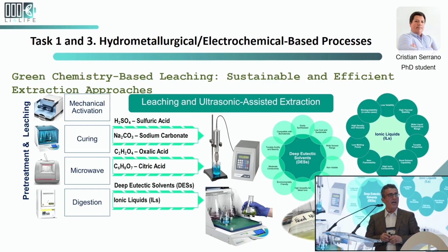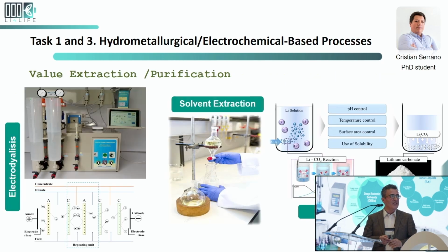These are our hydrometallurgical electrochemical processes. We are currently working on that and using different reagents: sulfuric acid, sodium carbonate directly, and also oxalic, citric, deep eutectic solvents, and ionic liquids. And we're using pretreatment, mechanical chemical activation, curing, microwave, and digestion in order to compare which method can replace the current high-temperature lithium extraction process.